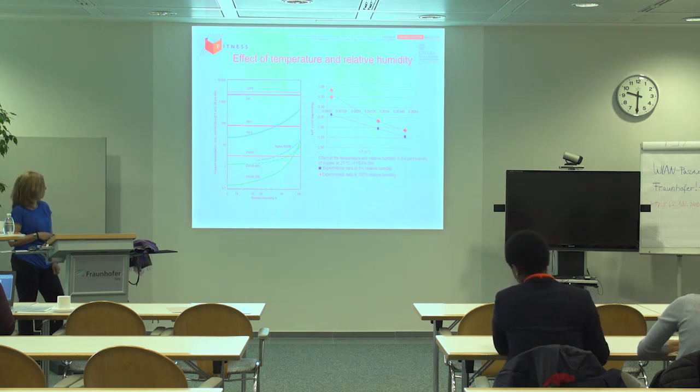When the humidity goes up, it loses the barrier properties to oxygen faster. Compared to the 44% EVOH that has, let's say, a not so good behavior, but then at high relative humidities is better.